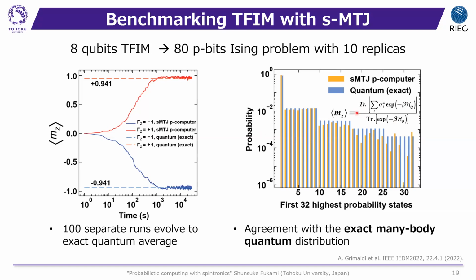And the right figure is important. So the orange bar shows the probability of the converged state for the first 32 highest probability states. And the blue bar shows the exact ideal distribution of each state. So at least the first and second probable states can be reasonably reproduced by the Spintronic-based probabilistic computers. So we observed a good agreement with the exact many-body quantum distributions. So this means that the probabilistic computers are also capable of addressing quantum problems by using the Suzuki-Trotter decompositions.